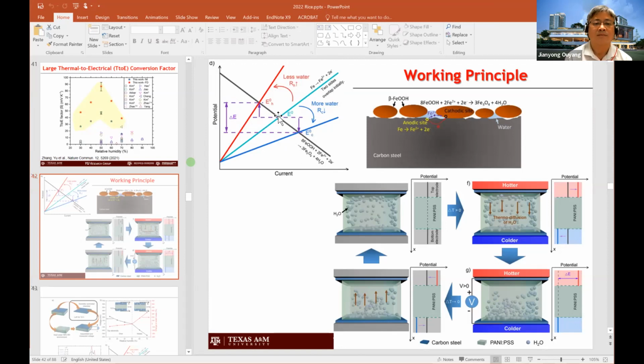So when we have less water, this line becomes upward, and you have a new established voltage potential. And when we have more water, it's like that. Initially both electrodes are the same. But once you have hotter and colder sides, the hotter side becomes less water and the colder side goes to the bottom. Then we have a temperature-induced voltage difference here. This is actually quite large.